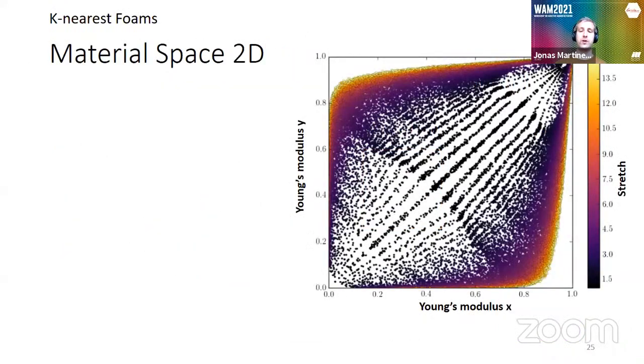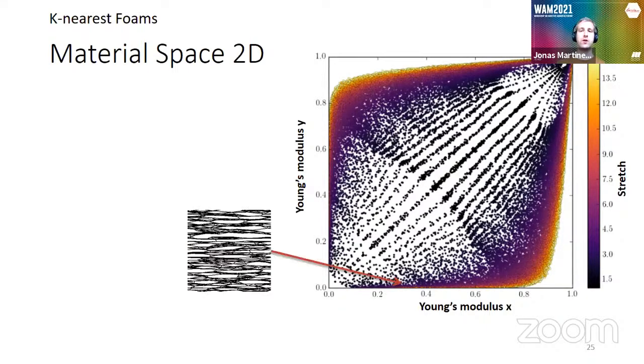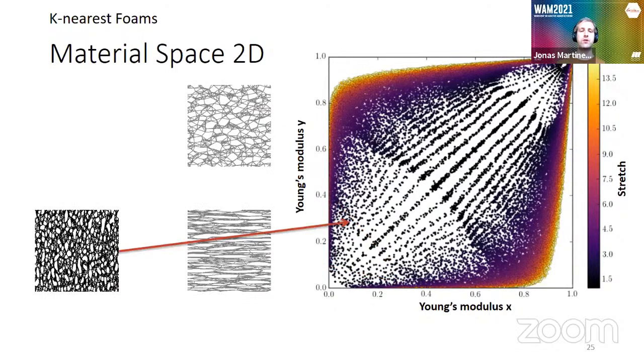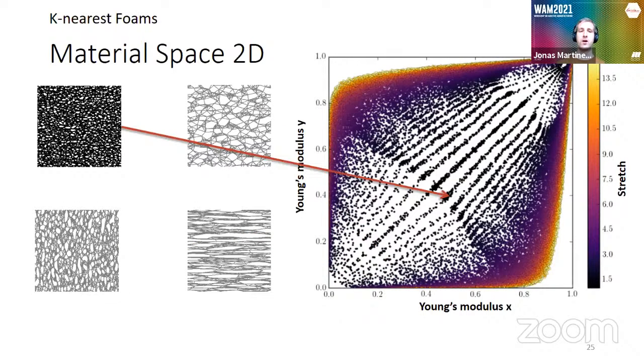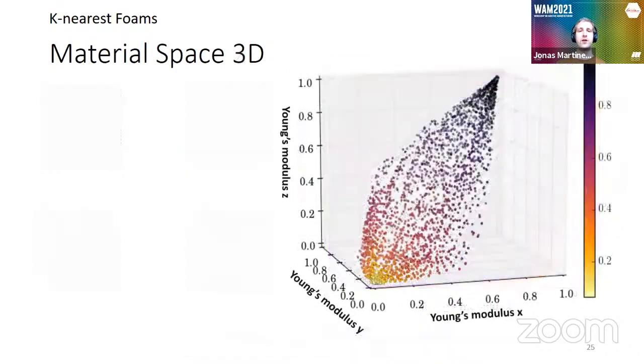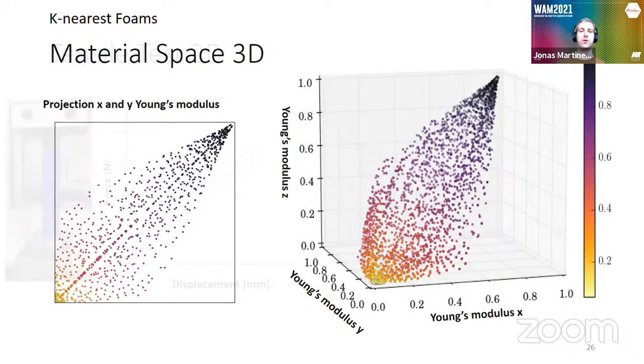Regarding the material space in 2D, one note: all these results are considering simple linear elasticity. So we just do periodic homogenization with linear elasticity. Here you can see the space we cover of Young moduli in X and Y. So it's a pretty wide space, and you can see some samples of this space. This is in 2D. And here the same when you lift up to 3D. So basically you have a set of points, and you have some 3D metric, and we also cover a wide space.